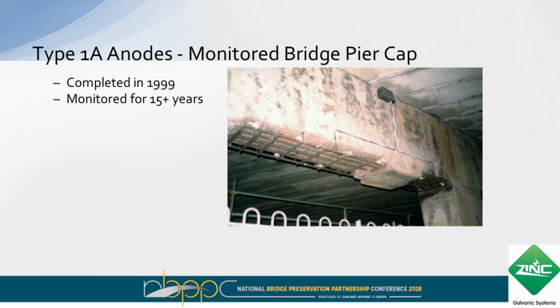This is a similar situation where you have the replacement of a parapet wall, and in this case, you're leaving the existing bars, the stirrups that are coming up out of the slab, but replacing the parapet, so you have this interface between the old contaminated concrete and then a new concrete section that's being placed for the wall. And just to provide a localized, targeted area of protection right there is an economical use of this type of system.